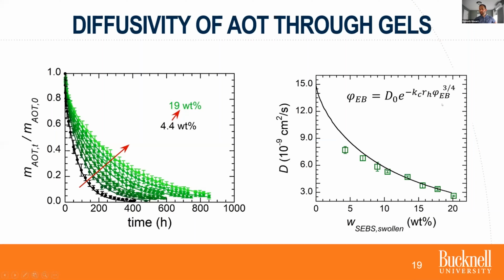It's important to note here, the scaling of this model is derived from mesh size arguments. And so this isn't taking any of the nanostructure of the copolymer into account beyond the mesh size calculations I showed you before. I should define here that there's a typo, sorry. This should be D on the left-hand side is equal to D0, which is diffusion through pure solvent, in other words, zero polymer concentration. Kc is a constant that corresponds to the polymer solvent system being examined. RH is the hydrodynamic radius of our probe, so that's the 1.7 nanometers I mentioned before. And phi EB is the volume fraction of ethylene butylene chains in the green space of the network.